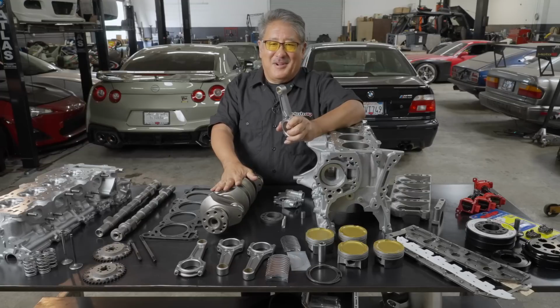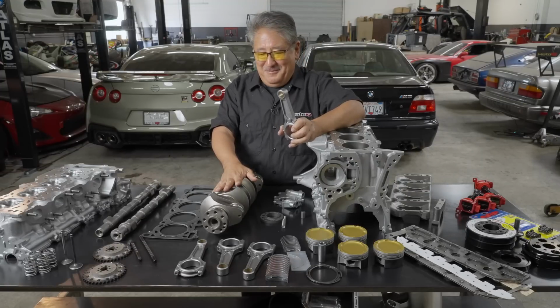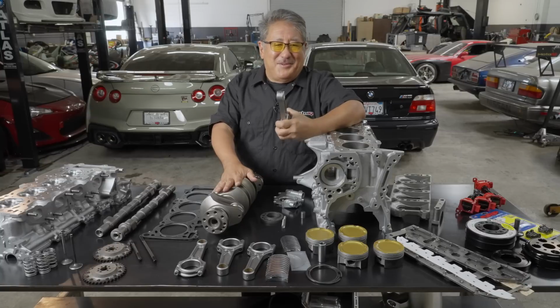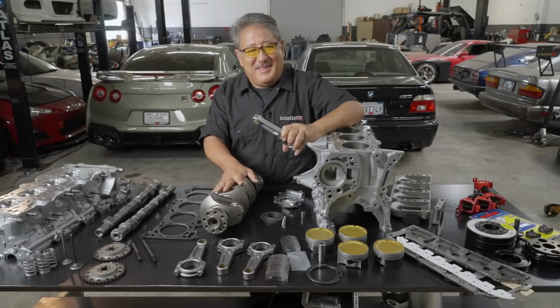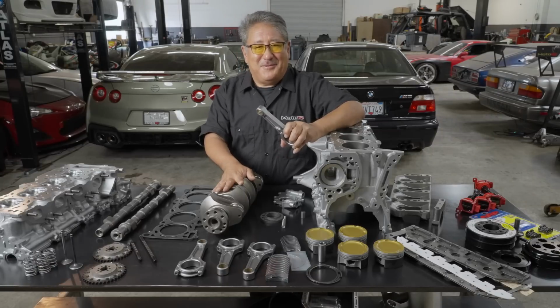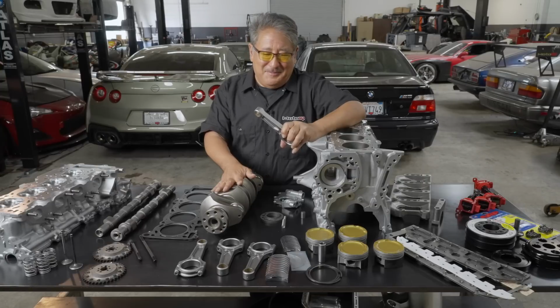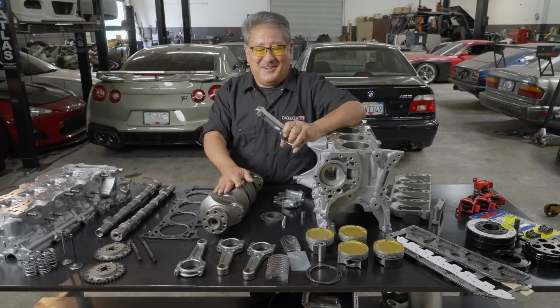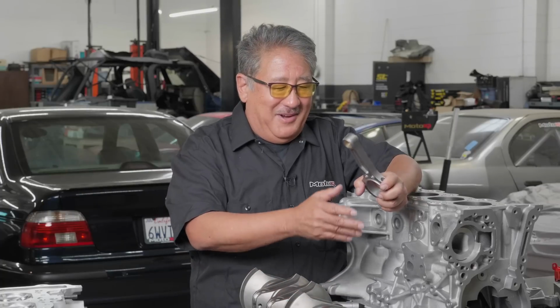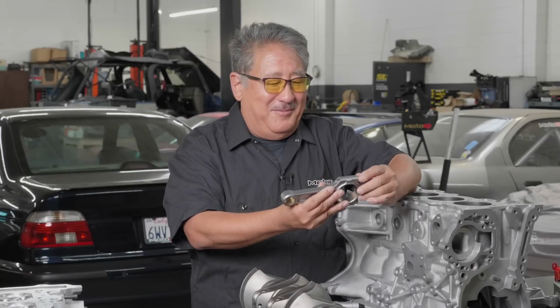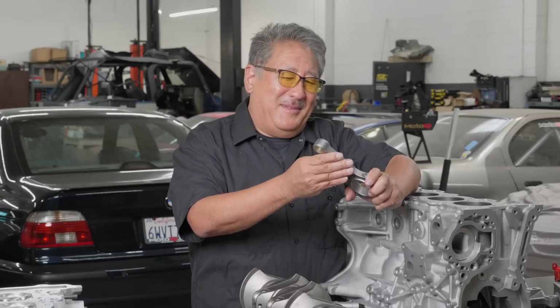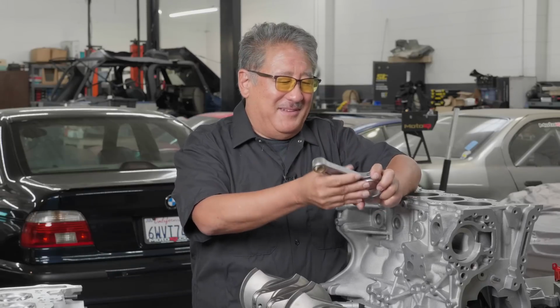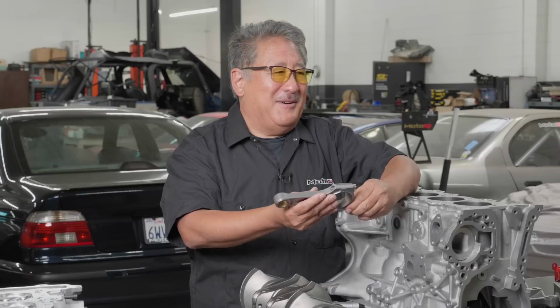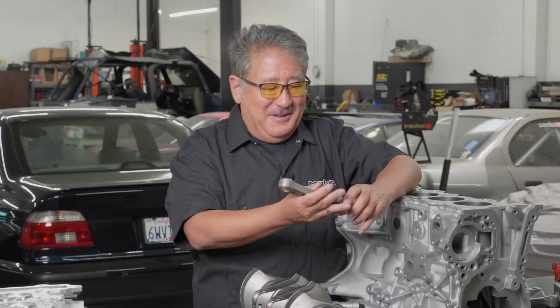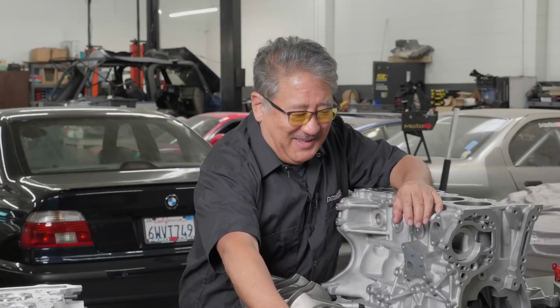We also subjected the crank and rods to CTP cryogenic treatment. For ferrous metals, the cryo converts a lot of the austenite into martensite. As we said before, it goes from a face-centered cubic to a body-centered cubic structure, which is harder and stronger with better tensile characteristics. We also WPC'd the crank and the rods. We did the whole rod and we did the bolts. This is a further refinement of the shot peening process, and for the small end of the rod, it makes everything slipperier. On the bolts, it should help fatigue strength and help us get more accurate torque. I think it's all wins for not that much more money.